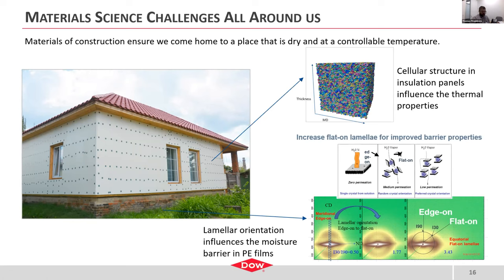We do this as a way to understand the effect of polymer resin design, so things like molecular weight distribution, comonomer contents, things of that nature, as well as the effect of polymer processing, so film line speed, extrusion, preferential orientation that is formed post-processing through pulled methods, things of that nature. So finding out ways that we can increase that moisture barrier are things that are really important to us.